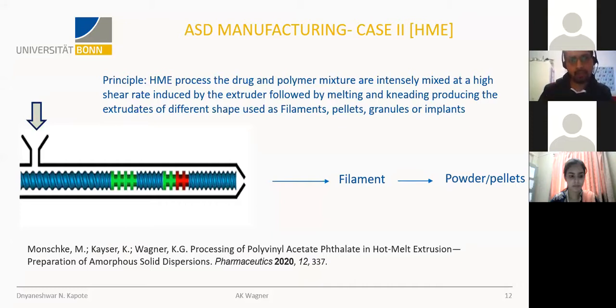So you start with adding your mixture. The conveying block conveys your material, your powder feed. It comes into contact with the screw. Due to the heating, the melting takes place, and due to the friction between the screws, another heating is being exerted. So the melting and kneading takes place inside the block, and after this there is a hole, which stands for the die. The filament comes out. You collect those filaments, and then you can downstream them into pellets or a powder or a granule or an implant.